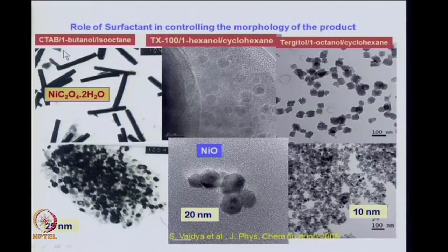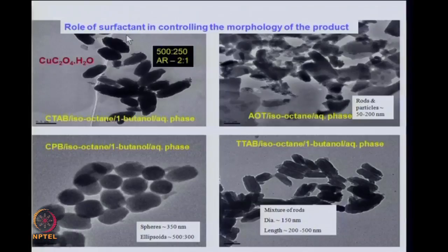And that is because you have changed the surfactants from C-tab, which is a cationic surfactant, to a neutral surfactant like TX100, to another neutral surfactant of a different size, which is tergitol, and you get different shapes of these oxalates. And if you decompose them, you of course get nickel oxides of different sized particles. So, you have 25 nanometer particles, 20 nanometer particles, and 10 nanometer particles based on the precursor that you use. And the precursor size you have controlled using the different surfactants in each case. So, this is another example of controlling the size and shape using surfactants.